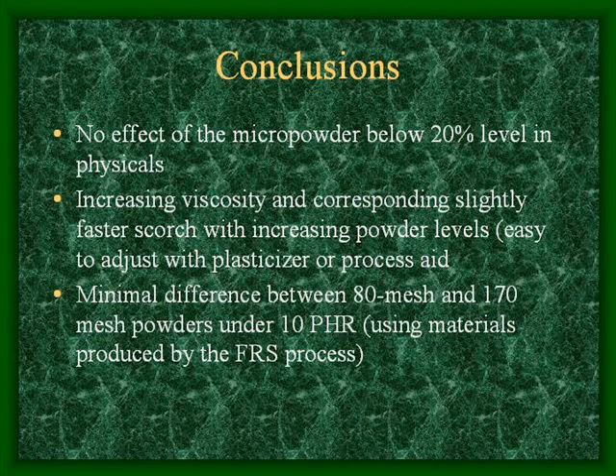In conclusion, there's minimal effect on physical properties of these micropowder samples under 20% in loading. There was an increasing viscosity and correspondingly slightly faster scorch with increased powder levels, but this is easy to adjust with plasticizer or process aid. And there were minimal differences between the 80 and 170 mesh samples in this experiment.